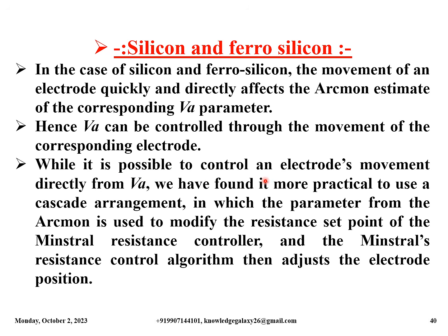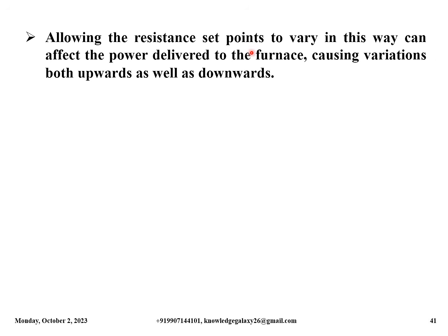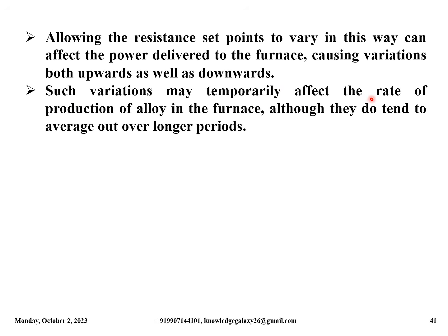While it is possible to control an electrode's movement directly from VA, we have found it more practical to use a cascade arrangement in which the parameter from the arcmon is used to modify the resistance set point of the Minstral resistance controller, and the Minstral's resistance control algorithm then adjusts the electrode position. Allowing the resistance set points to vary in this way can affect the power delivered to the furnace, causing variations both upwards as well as downwards. Such variations may temporarily affect the rate of production of alloy in the furnace, although they do tend to average out over longer periods.